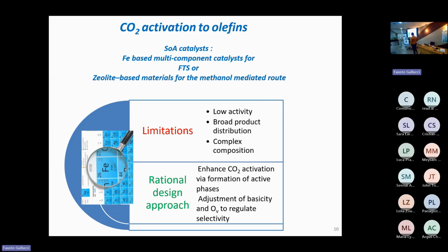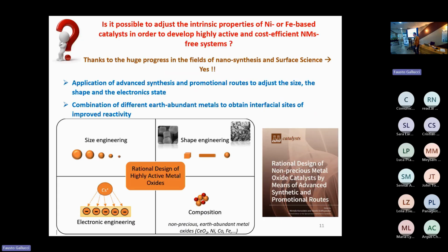On the other hand, for the most demanding process, the CO2 activation to olefins, the state-of-the-art catalysts involve iron-based multi-component catalysts for the Fischer-Tropsch route, or zeolite-based materials for the methanol-mediated route, both suffering from low activity, broad product distribution, and complex composition. In this case, a rational design approach should be focused on the enhancement of CO2 activation via the formation of active phases, like carbide phases, and on the adjustment of acidity and oxygen vacancies to regulate the selectivity. At this point, a key question is raised: is it possible to adjust the intrinsic properties of nickel or iron in order to develop highly active materials?